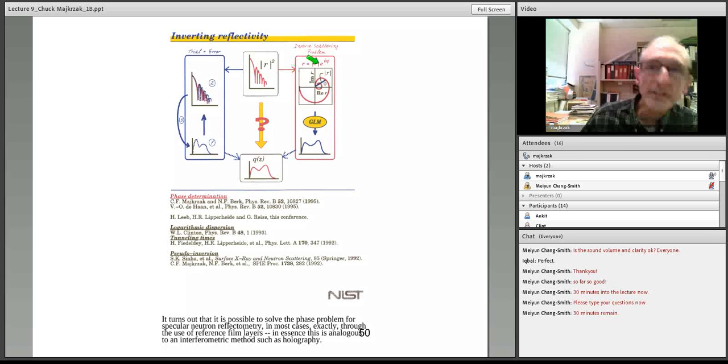If we had the phase information, if we were able to measure the reflection amplitude, so you have the complex quantity, the real and imaginary parts, then it turns out in this one-dimensional case for specular neutron reflection with no appreciable absorption, there exists an integral equation solution, a glorified Fourier transform, if you like, called the Gelfand-Levitan-Marchenko solution that can be applied to give you, from the measured reflection amplitude, an exact, unique scattering length density profile, one-to-one correspondence.